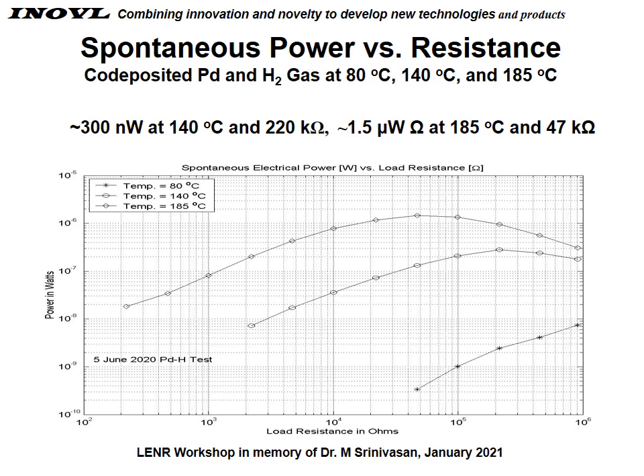Here are the plots of spontaneous power versus resistance. This is for 80, 140, and 185 degrees C. And you see the power peaks and then goes down. You can see that at the highest temperature the power peaks higher, and it peaks at a lower ohm resistance, which is a higher load. And actually this behavior is what you would expect for some types of power supplies.